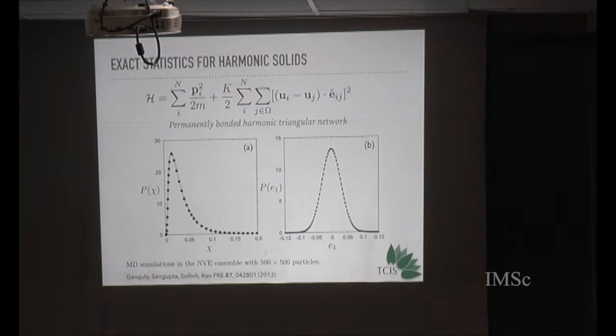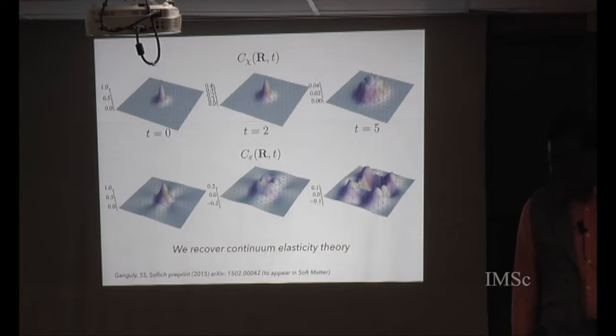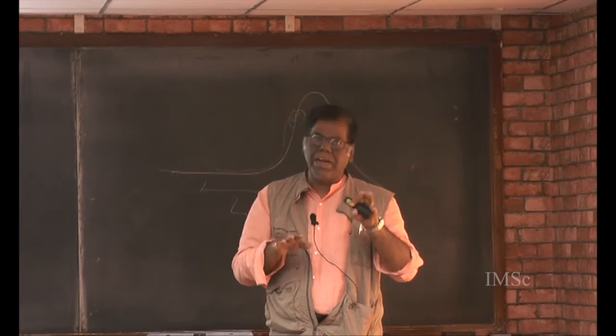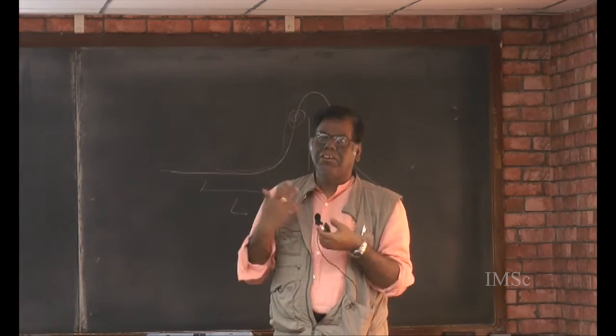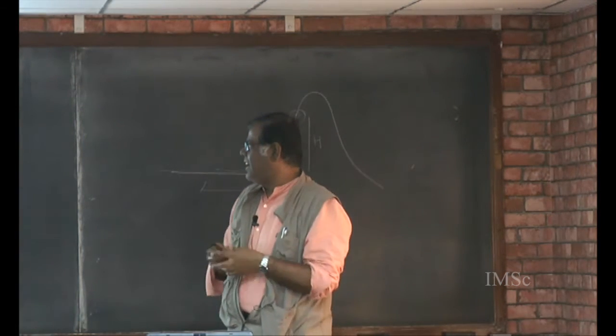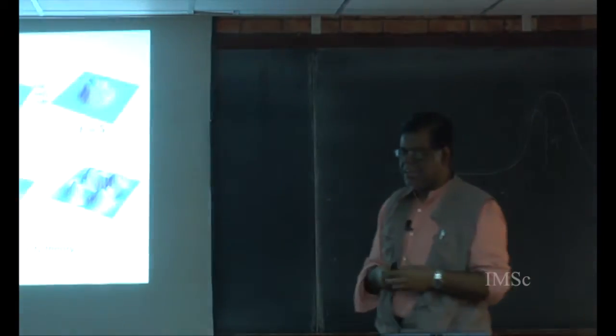And if you have a simple Hamiltonian for which you know the dynamical matrix, then you can calculate things exactly. So these are our calculations for a permanently bonded harmonic triangular network. That's just one of the simplest non-trivial crystalline solids that you can imagine. Dots are simulations, lines are exact theory, and as you can see, they are exact. You can calculate correlation functions of both the non-affine and the affine part, and you can show that continuum elasticity theory, with its equations of mechanical stability as well as Saint-Venant compatibility conditions, all of it falls out from this. So this is all compatible with compatibility. Okay, so continuum elastic theory is recovered from this. Okay.